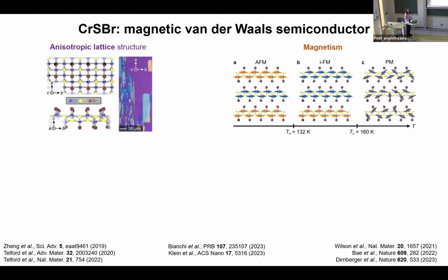CrSBr has a series of magnetic phase transitions. Below the Néel temperature of 132 Kelvin, the in-plane spin arrangement is ferromagnetic. However, the interlayer coupling is antiferromagnetic. This is what we call A-type antiferromagnetism.